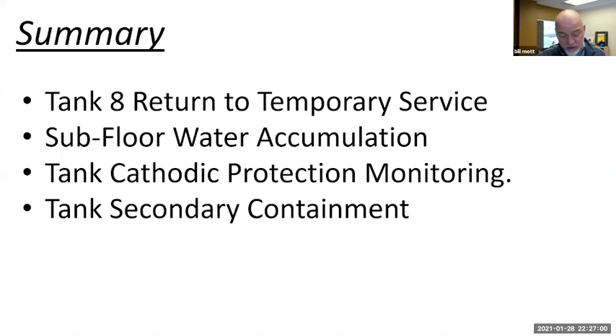In summary, on the tank 8 return to temporary service, I think the approach they took was pretty conservative. I think the corrosion rate they used was quite conservative. I think there's a very low risk that you're going to have a corrosion problem in the floor of that tank before it's removed from service in 2023 for a new floor and a new CP system.